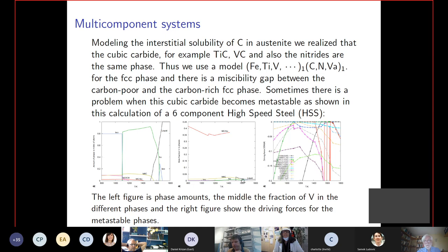And you can see the composition of that phase varying the temperature. And this I was told was interesting for doing. I don't really deal with phase transformations, but when you deal with phase transformation, you like to know how stable other phases are relative to the ones you have. And this is a calculation showing the driving force for forming different phases varying the temperature. All these curves are from one calculation. You calculate one range and then you can plot different properties from that one.